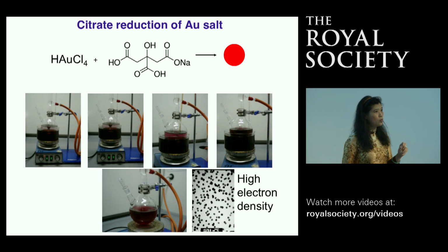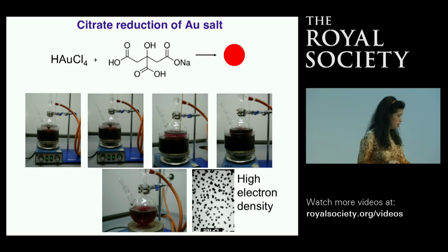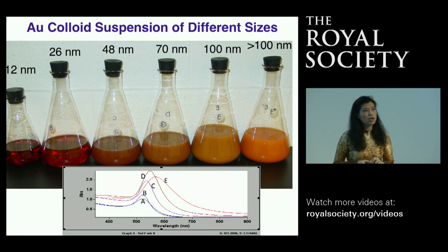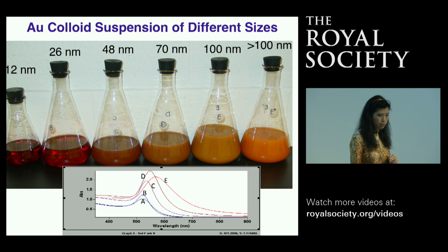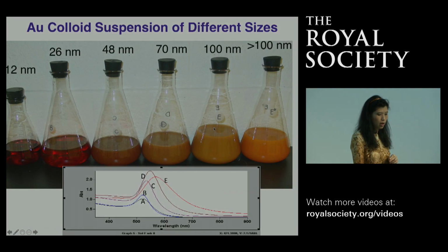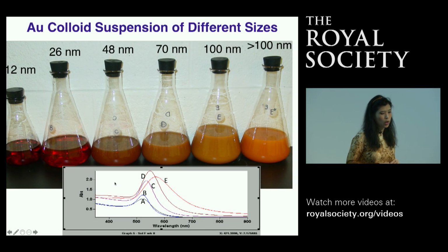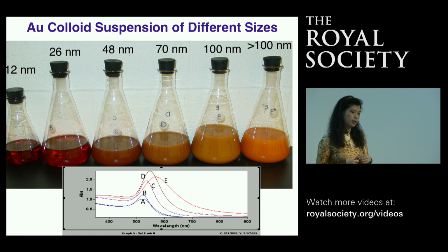And that is how the gold nanoparticles look under a transmission electron microscope, because gold has a very high electron density. So gold is the easiest element for us when you look under the TEM. You can make nanoparticles of different sizes, and they have different optical properties. And you can see that under the UV spectrum, let's say solution A is equivalent to 12 nanometer gold nanoparticles.